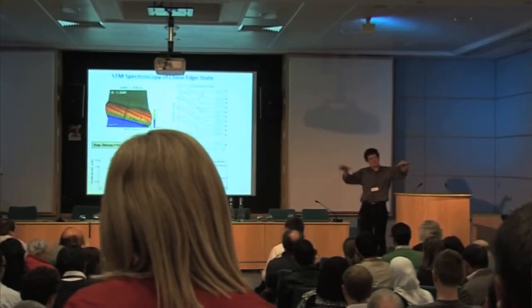Sure. I suppose the test would be to actually look at a substrate that was restructured, and see whether you still see the same STM features. But you're saying the graphene would have to provide enough strain to cause the platinum to do that. Well, if you form the graphene at high temperatures, where there's enough atomic mobility of the substrate, they do restructure into pyramidal.